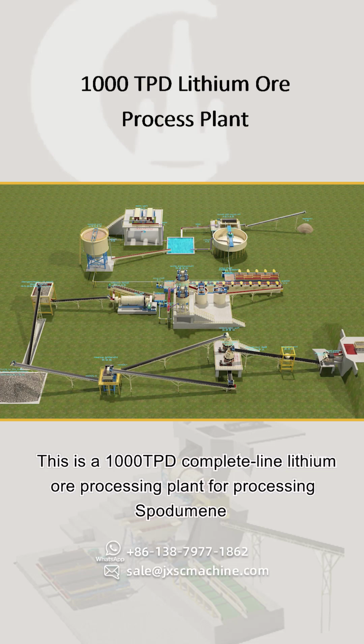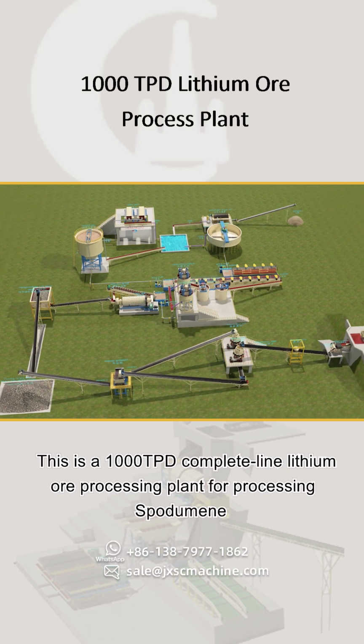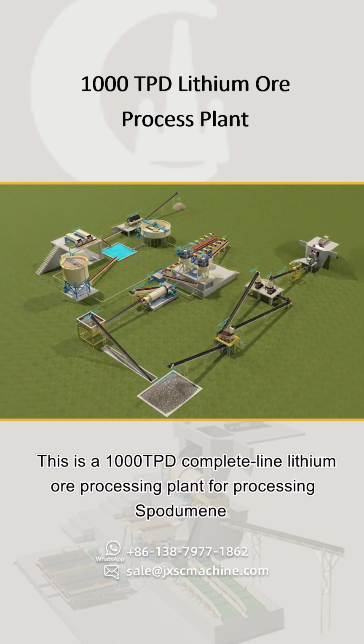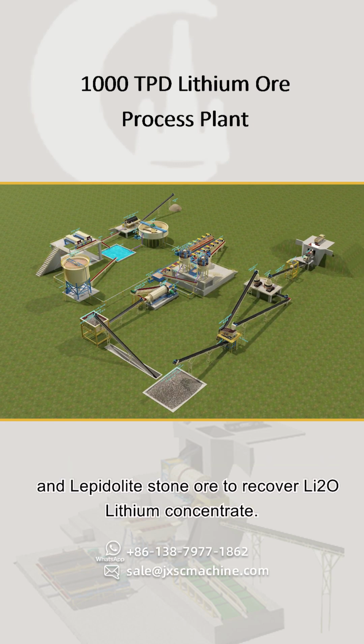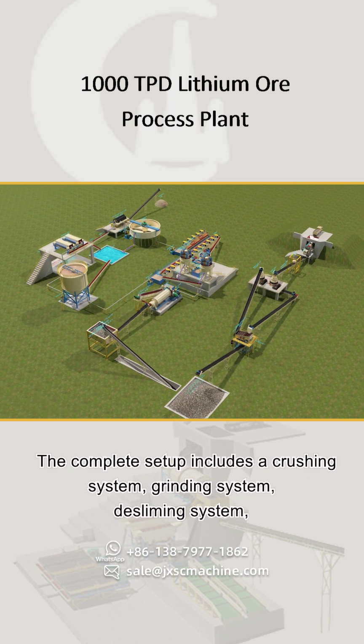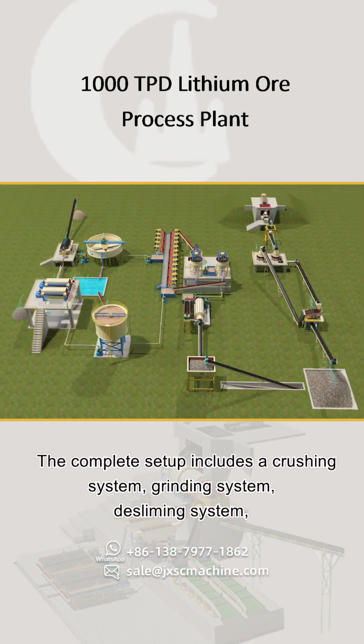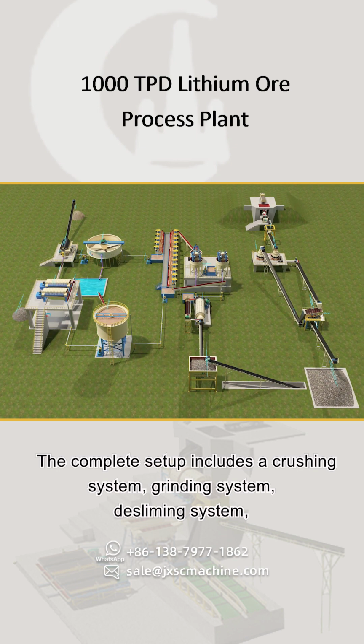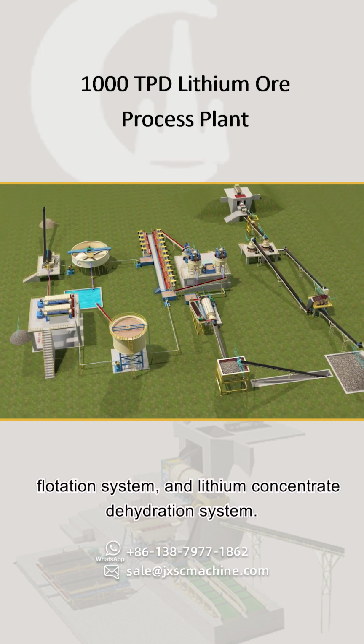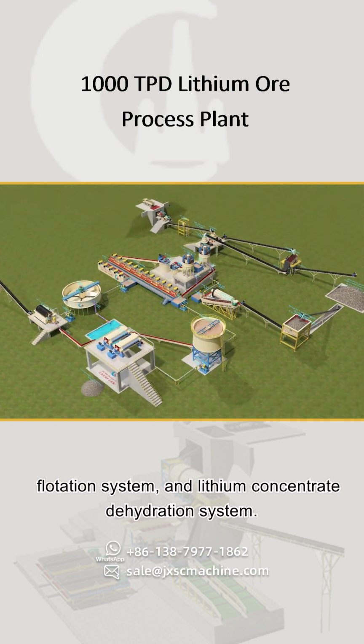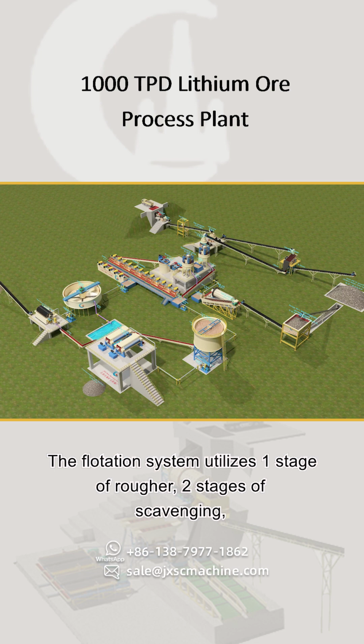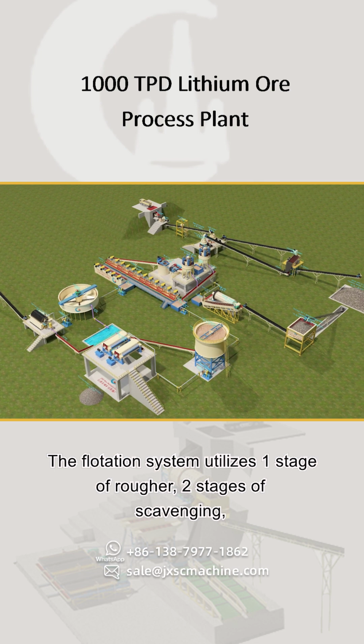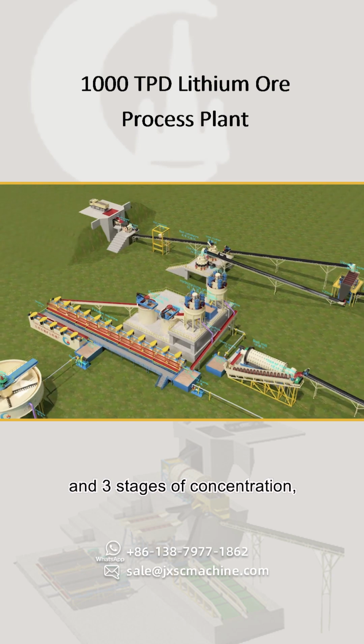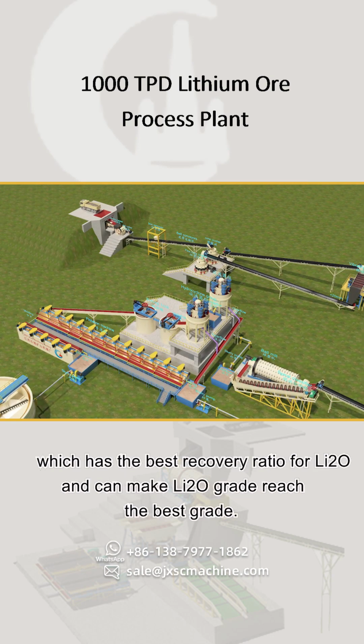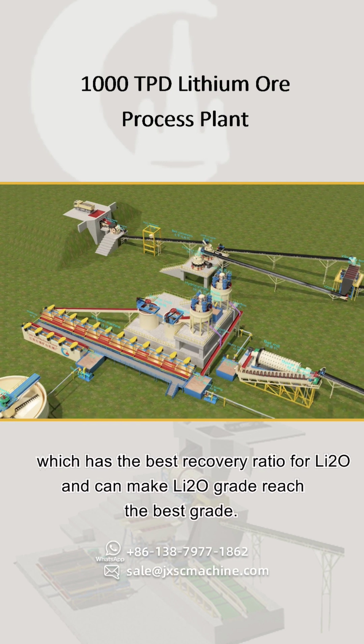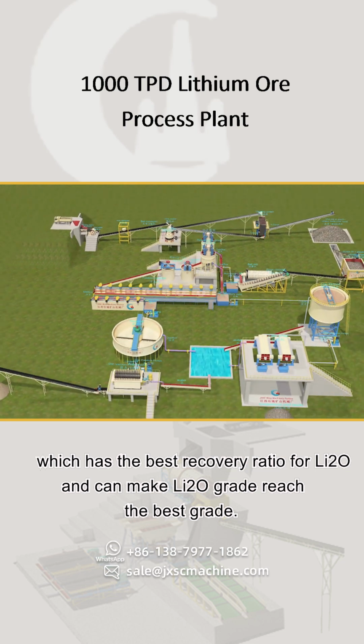This is a 1,000 tons per day complete-line lithium ore processing plant for processing spodumene and lepidolite stone ore to recover Li2O lithium concentrate. The complete setup includes a crushing system, grinding system, desliming system, flotation system, and lithium concentrate dehydration system. The flotation system utilizes 1 stage of rougher, 2 stages of scavenging, and 3 stages of concentration, which has the best recovery ratio for Li2O and can make Li2O grade reach the best grade.